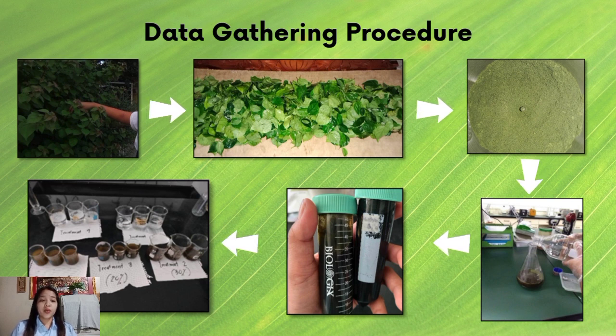Bougainvillea spectabilis extract will be tested and exposed in different concentrations to observe the efficacy using weight loss measurement. The corrosion inhibition activity of Bougainvillea spectabilis leaves crude extract was tested using 5 treatments, including 3 different concentrations of the Bougainvillea spectabilis leaves, which are 30%, 20%, and 10%. The other 2 treatments represent the positive control, which is the commercially available corrosion inhibitor, 84 ml of Turco Rust converter, and lastly the negative control, which is 85 ml of 1 molar hydrochloric solution.